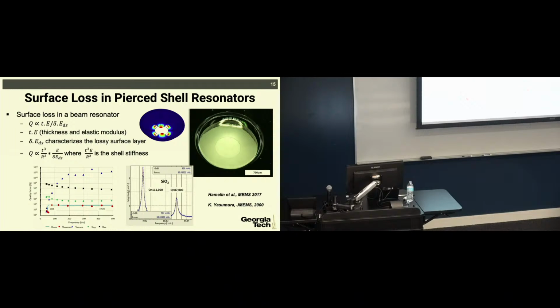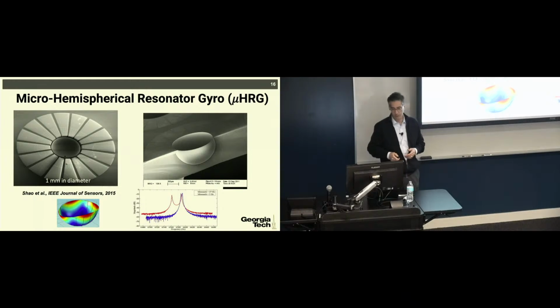So this was a way of indirectly measuring the surface losses in silicon dioxide, which is proportional to this delta. Delta is the thickness of the lossy layer on the surface of the shell. As you can see here, this ratio, which is the thickness of the shell itself over delta, times the modulus of silicon dioxide versus the modulus of that lossy layer, would determine what the surface losses in the resonator would be. So, long story short, if you are thinking about getting Qs in excess of 1 million or so, you can't really use thin films, because this ratio of T over delta would be limited. Your thicknesses are small, the delta would be on the order of 1 nanometer or so. So you're going to be surface loss limited and you won't be able to get to extremely high Q factors, okay?